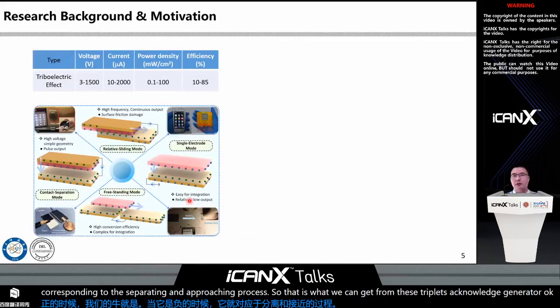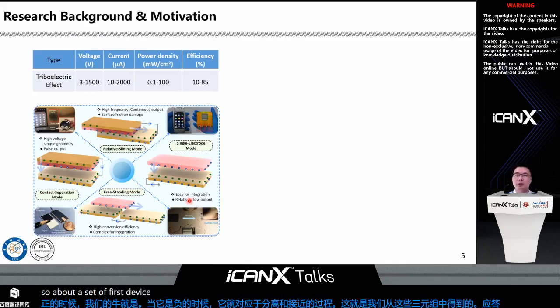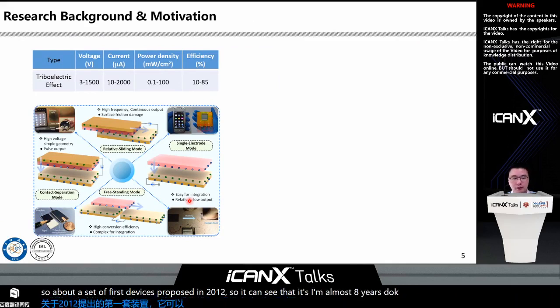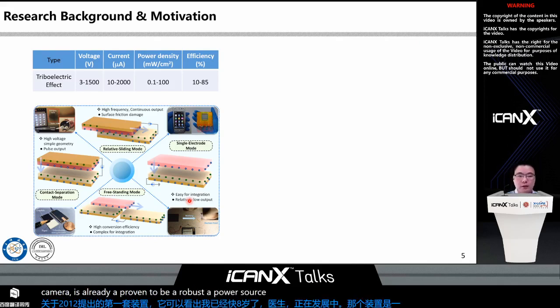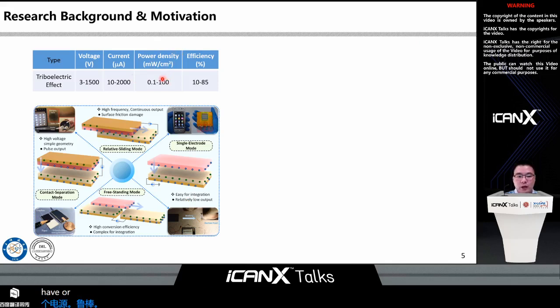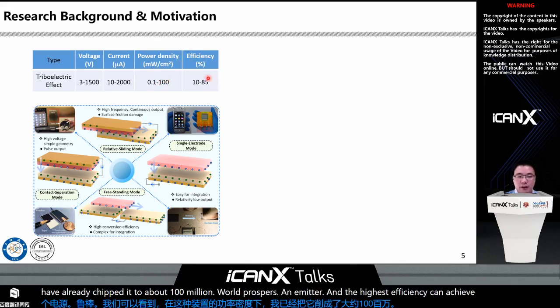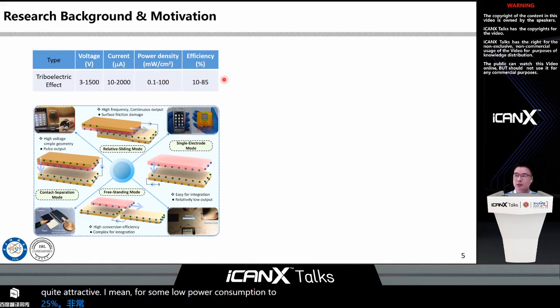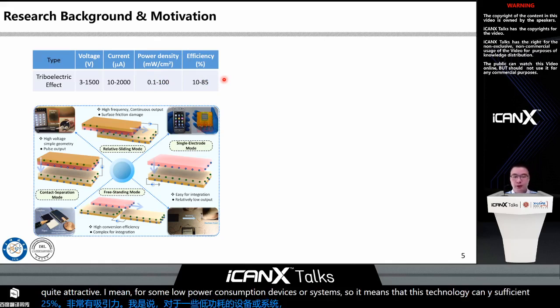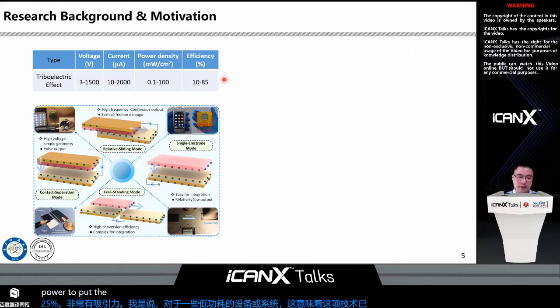Since the first device was proposed in 2012, after about 8 years of development, the device has already been proven to be a robust power source. Here we can see that the power density of this kind of device has already achieved about 100 milliwatts per square centimeter, and the highest efficiency can reach 85%. So it's quite attractive. For some low power consumption devices or systems, this technology can provide sufficient power.